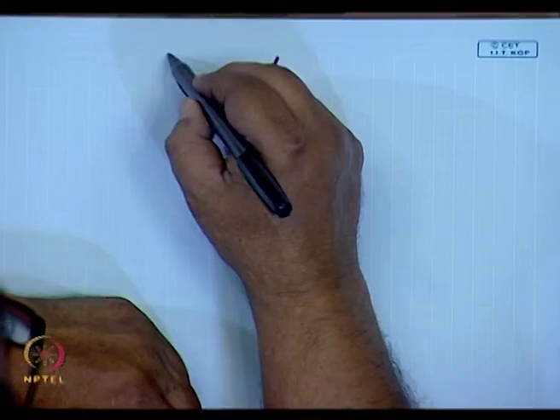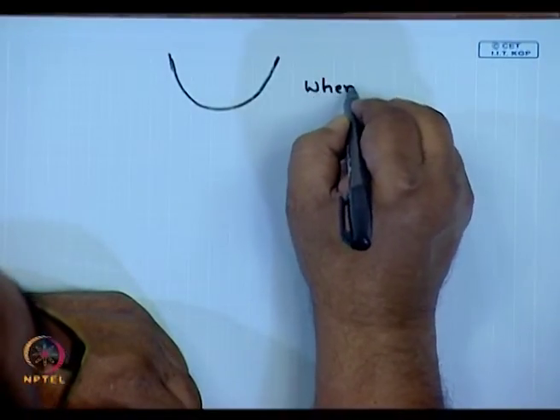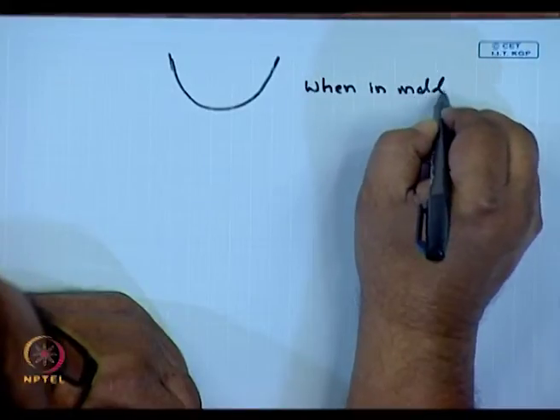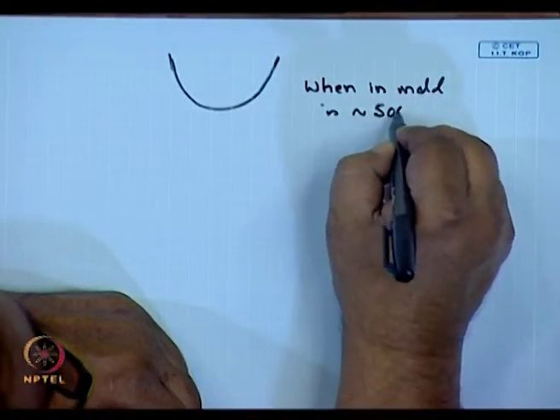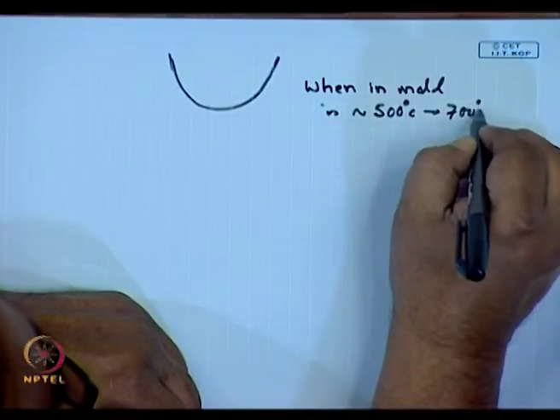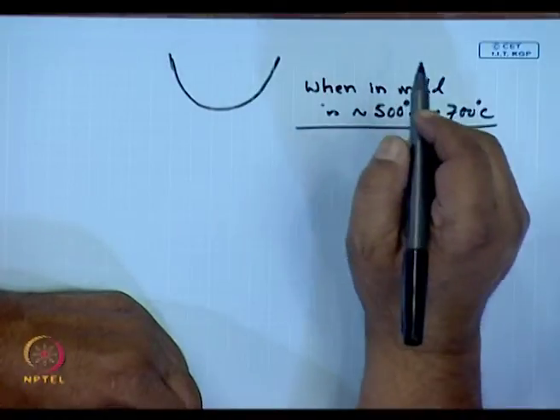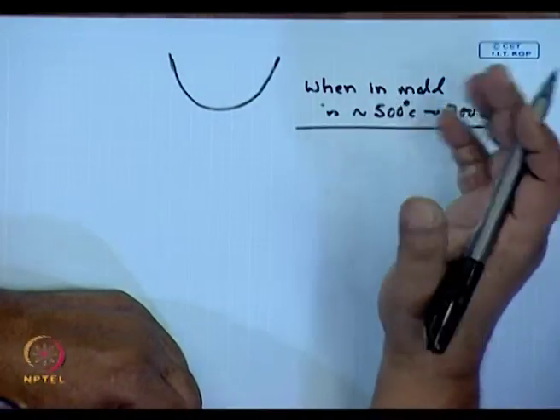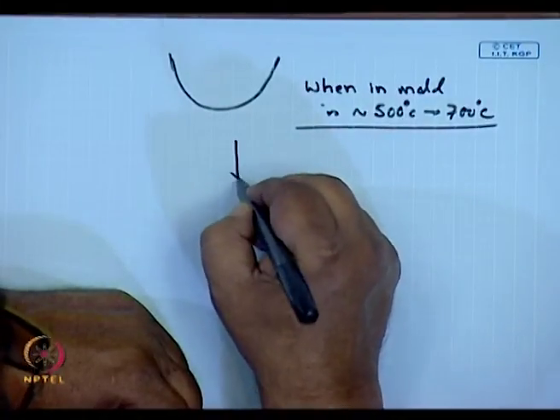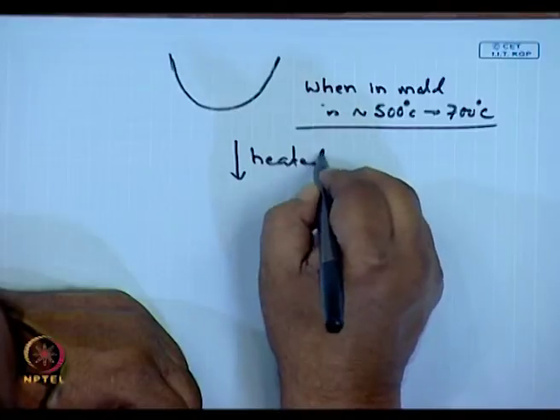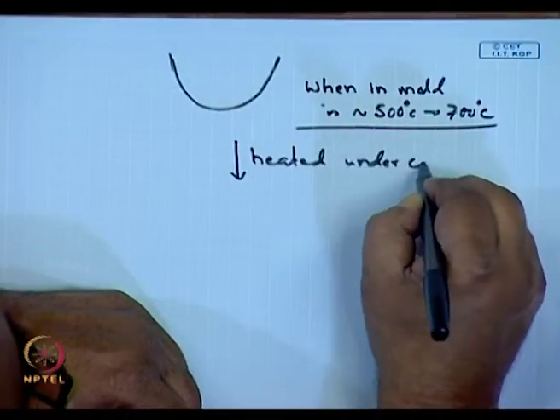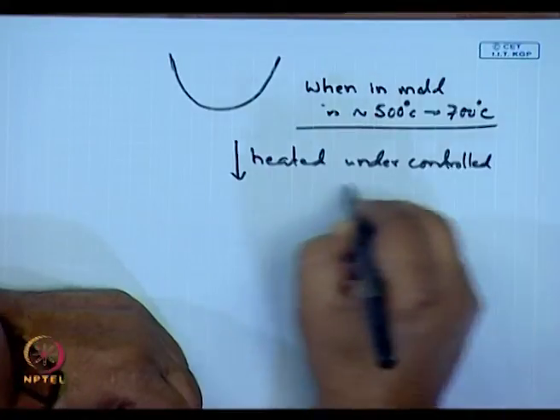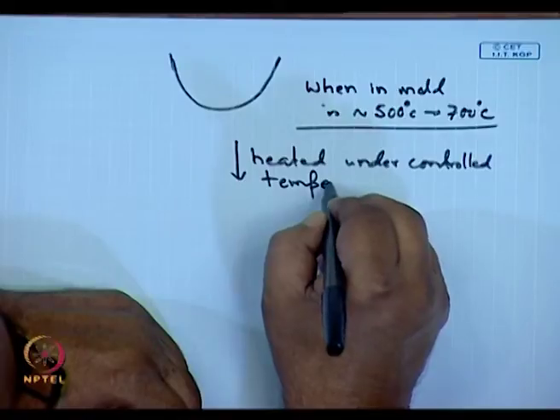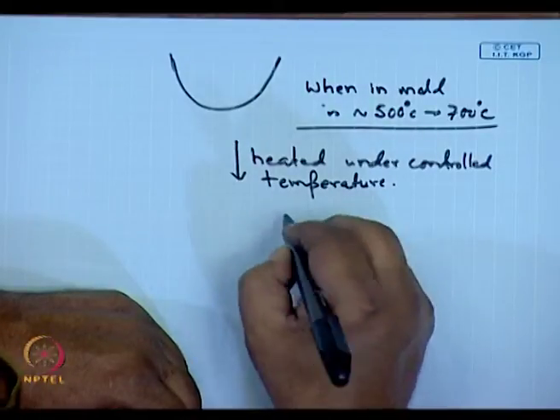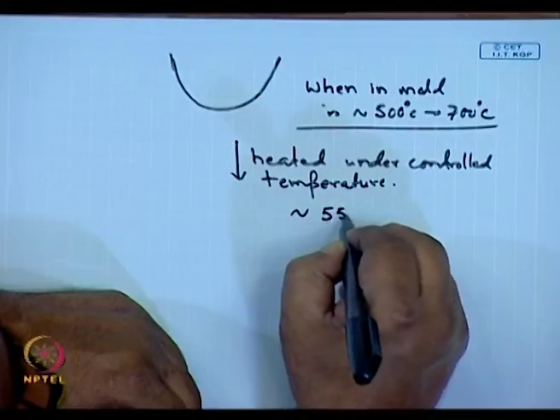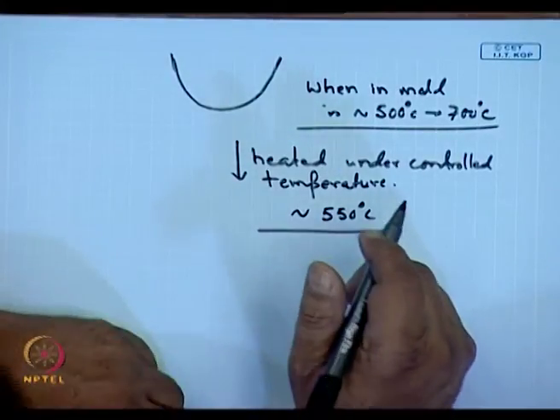So this shape, when in the mold, is anywhere between 500 degrees centigrade and 700 degrees centigrade. It's a rigid body. Of course, it will deform if you apply pressure. This is then heated under controlled conditions, somewhere around 550 degrees centigrade, and this is where something happens.